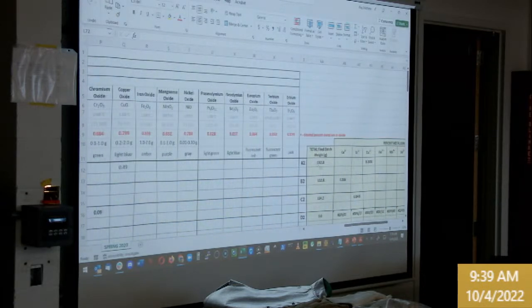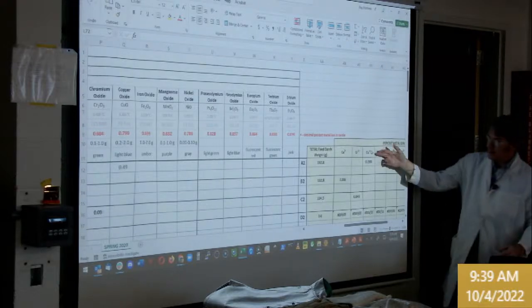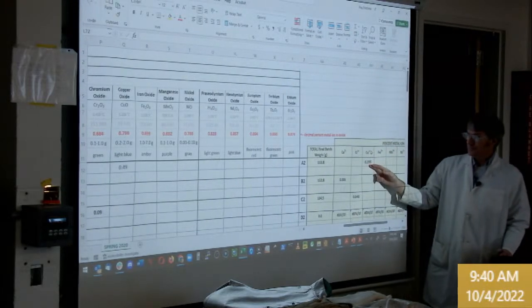Okay, so let's just pick a composition. Let's say we're picking on A here. So we've got the silica, sodium carbonate, calcium carbonate. These are generic chemical names. They're not specific to the type that you use, but this gives you the batch mass. And so we added 0.49 grams of copper oxide in batch A and a little bit of aluminum oxide. So with those inputs, we can then calculate what our total fired batch weight would be and the final percentage of copper in that glass. So that's all found over here.